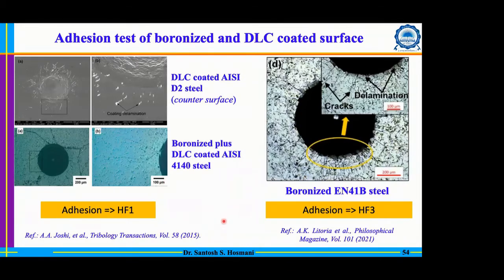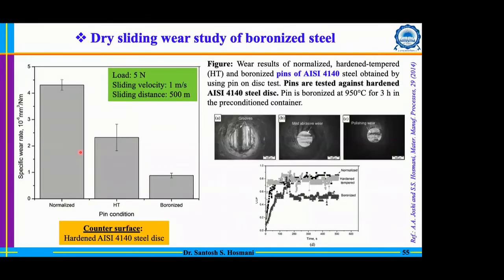Now, if you deposit a coating like a DLC coating on the surface under the same load, you can see that your adhesion is further improved. That means, in principle, a very thin layer of DLC can be useful, especially to avoid any kind of cracking during the interaction in application. So that is beneficial here. In principle, you have very good adhesion for the boronized layer, and it can be further improved by using the coating. And this bar graph clearly shows the boronized surface is performing very well compared to the normalized and heat treated condition.